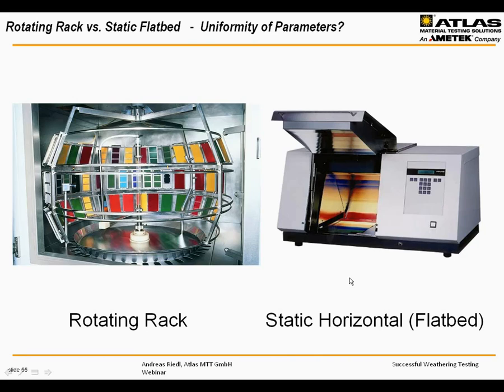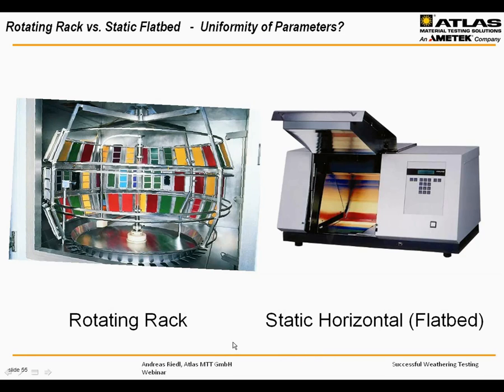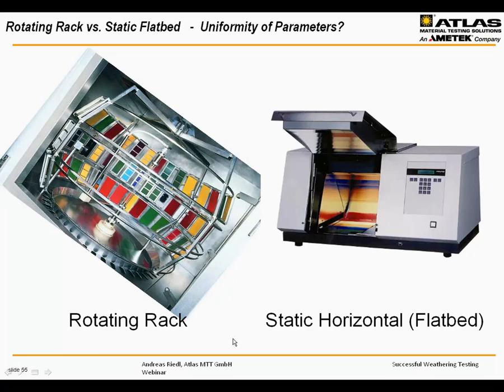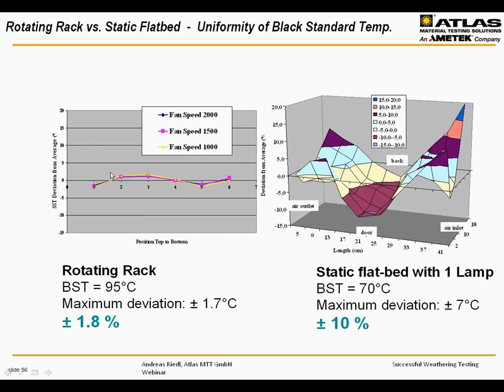Let's compare rotating rack and static horizontal. This is just a smaller instrument with one lamp here. And if you put that to the side here, if it were possible, it's a big instrument, it's not possible, but just for showing the data, then you can look at these data here. And these are specimen positions 1, 2, 3, 4, 5, 6, from bottom to top. You saw that we rotated that instrument at different fan speeds. Don't care about that. It's just showing that the conditions stay the same here, minus 5, plus 5 Celsius, and you see the maximum deviation in temperature. If you have a black standard temperature of 95 Celsius, which is quite high, the maximum deviation is below 2% from that, 1.7 Celsius. That's quite narrow.